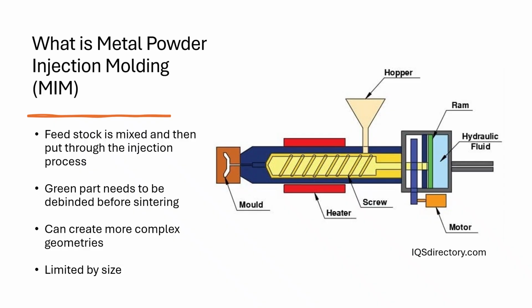First, you have to create a feedstock, which is just a mixture of powdered metal and wax. After you have created this feedstock, you place it in the hopper of the molder. Then this material travels through the heater, which heats up the material, making it much more of a liquid, before this liquid is injected through the gate of the tooling part in order to fill the mold. Now, once the mold is completely filled, the tooling part opens and allows the part to be released from the mold. This part is now called a green part.